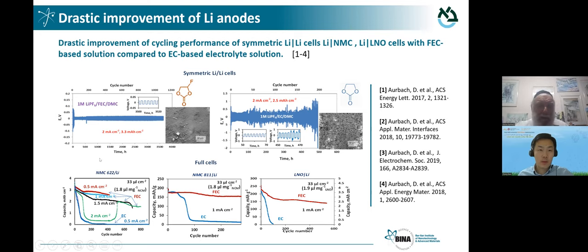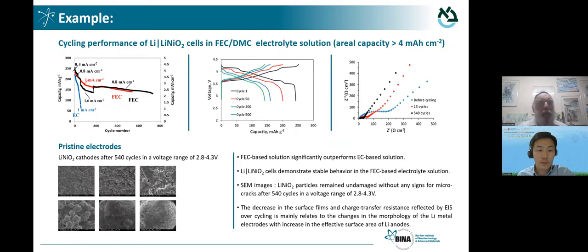So now we can take nickel-rich NCM cathodes. You have 60% nickel, 80% nickel, and even 100% nickel. And we see stabilization of full cells. Here we start with nearly 240 mAh/g with LNO, and we demonstrate stabilization over hundreds of cycles. Now there's a question: why, with symmetrical cells, when we have the reactive lithium, do we have thousands of cycles, and when we add a cathode, the number of relevant cycles is lower? The answer is that we have crosstalk between the electrodes, and we'll demonstrate it. But let me just concentrate on LNO.